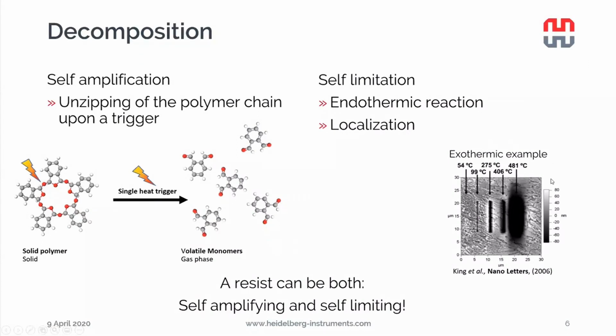If we have an exothermic example and we start to pattern at different temperatures, like in this example of King, they used a polymer that is exothermic. Then if you pattern at a lower increased temperature, the lines get a bit wider because you input more heat. And at this point, what we think happens is basically a small runaway reaction, that each of this breaking of the bonds created a new heat source that started to spread more heat and triggered more chain breaking events, and basically got a very wide patterning and running. Basically a small runaway reaction that created a big pattern that's also quite unwanted.